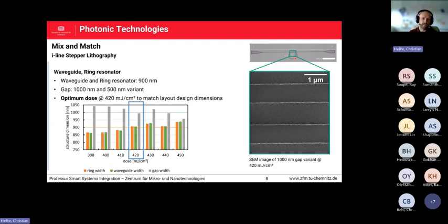Then we tested everything with the real PIC layout, meaning we exposed here waveguides and ring resonators with our I-line tool, and again checked at which certain dose we could reach the structure dimension of, for example, you can see it here with the 900 nanometer of the waveguide width and the ring width, for example. And of course, at the same point with the same exposure dose, you have to deal with the gap in between the ring resonator and the waveguide, for example.